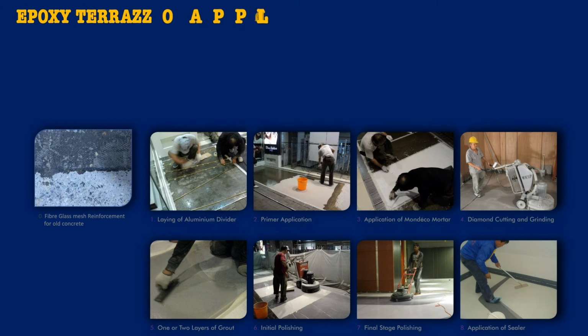We will now briefly demonstrate laying of epoxy terrazzo flooring. Please note that the base concrete has to be minimum M25 grade and above. First step is light grinding of concrete to expose surface pores. A uniform coat of epoxy moisture-tolerant primer will then be applied over concrete. While primer is still wet, provide a layer of fiberglass mesh to prevent cracks in concrete extending to terrazzo. Broadcast sand over the wet primer to act as mechanical key for subsequent coats.